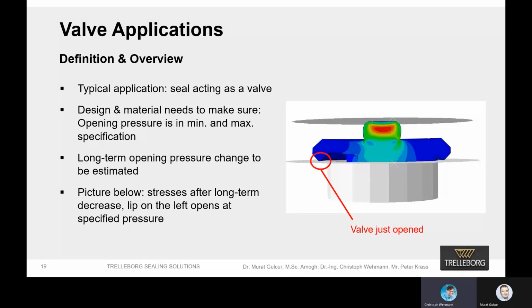On the next slide, I would like to show one application we applied this method to. It's an automotive application where the seal has a valve function. You see in red the area where the valve opens at a certain opening pressure. Here it's important that we can guarantee over the lifetime, which is approximately 20 years, that the opening pressure is within a certain tolerance. So it should not be below a minimum and not above a maximum. In the beginning, it will be close to the maximum, and then it will decrease over time, over years.